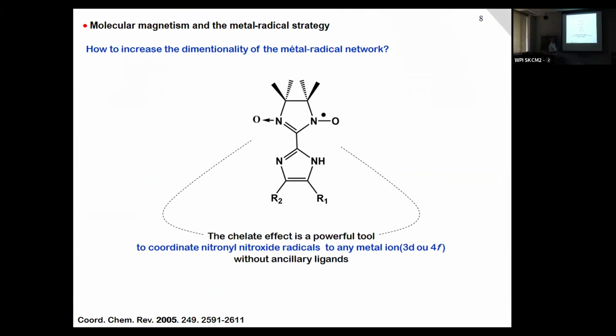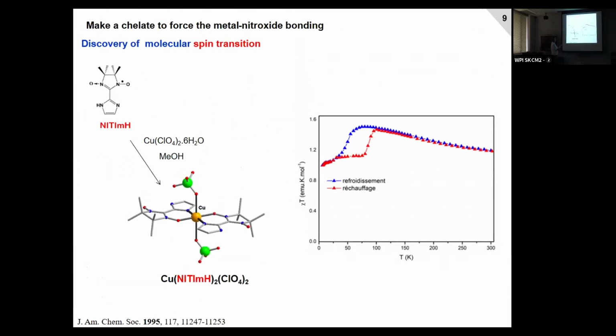And it is what I developed when I joined the group of Paul. My idea was to make the nitronyl a chelate ligand. If you make the chelate, it means the ligand will behave like pincers, so we can tie the metal ions. So here you have a chelate. And when you do this, it becomes easier to coordinate metal ions. For example, here I coordinate copper, and you see I no longer need to use the hexafluoroacetylacetonate I used before. The chelate effect is enough to coordinate the copper. And it was the first compound I made when I arrived in Grenoble. So I arrived in Grenoble the 10th of January.